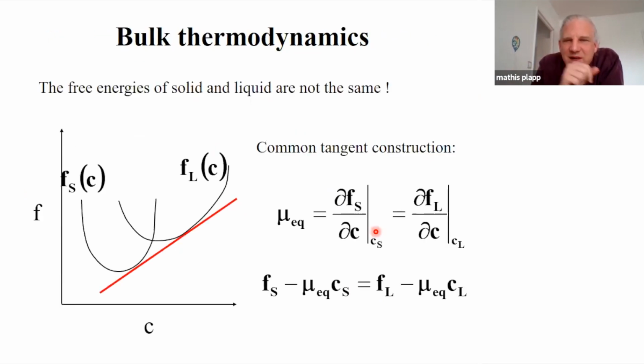And in addition, the free energy density is also different in the solid and the liquid. And why are they not the same? Well, you might remember how you construct a phase diagram of a mixture. For a binary mixture, you use what is called the common tangent construction. If you have a free energy function for the solid and for the liquid, you will have to find the common tangent, that is the tangent that touches both curves in a point. And then the compositions of solid and liquid will be these touching points. And in more thermodynamic terms, this will correspond to the condition that the chemical potential has to be equal in both phases. And this combination F minus mu C has to be the same in both phases. So this can be called the grand potential. It's not strictly the grand potential, but it's something that is really analogous to the grand potential.